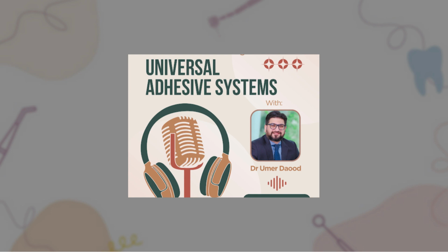Self-etch and universal adhesives have a less acidic composition compared with phosphoric acid. Thus, there's always a chance that it will reduce the potential to demineralize the fully mineral phase of the enamel and consequently not create appropriate micro-retentive porosity. So that can be an issue upfront.